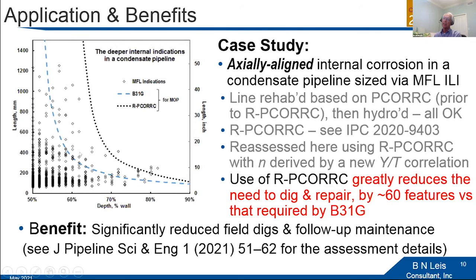And I've got two predictions here. So the indications are found by the inline inspection tool. That inspection was validated. One of the failure criteria here is the early failure criterion, B31G. This criterion here is PCORRC, and actually the revised version of PCORRC as well, because for this particular case, a criterion with strain hardening exponent and the UTS differs a little from that of the early work that was based solely on the UTS. What you see in this band between these two criteria is roughly 60 features.